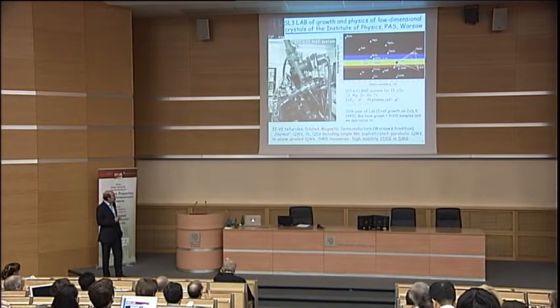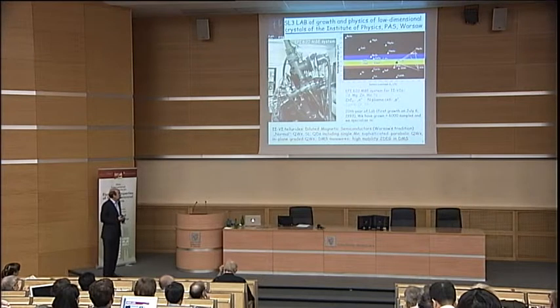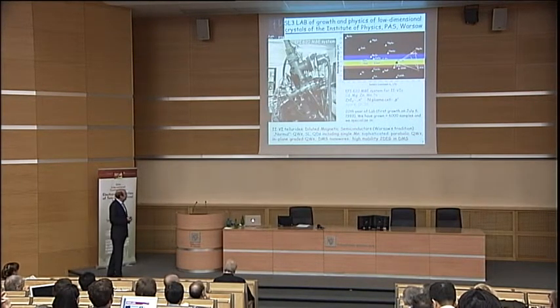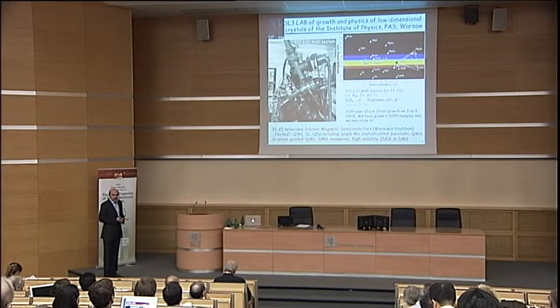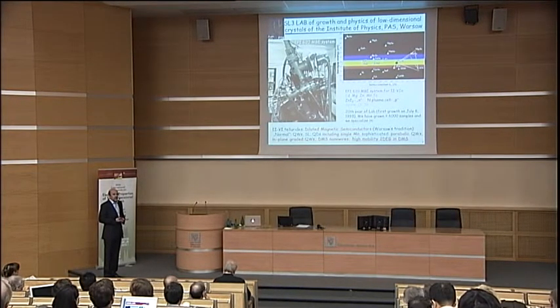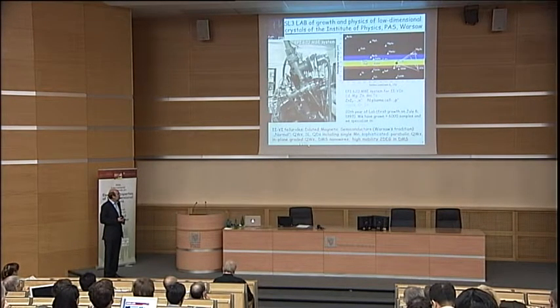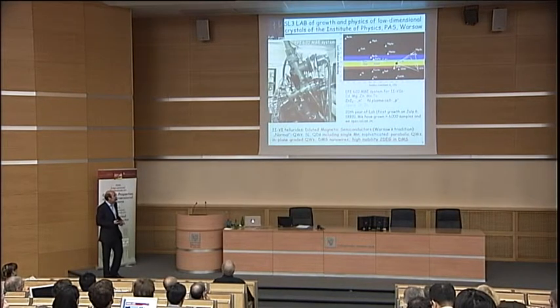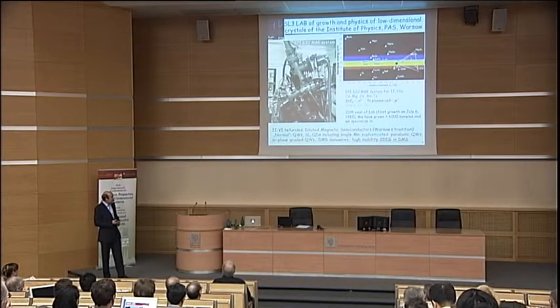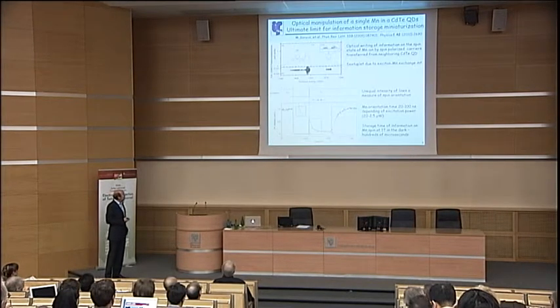And so we can only grow II-VI tellurides, as I mentioned, and then we, of course, specialize in diluted magnetic semiconductors, and that is probably the reason for this invitation, which is, on the other hand, Warsaw's tradition, as you might know. And apart from normal quantum wells, superlattices, and quantum dots, we also grow more sophisticated structures like parabolic quantum wells, in-plane graded quantum wells, DMS nanowires, or the major subject of my talk, 2DEG.